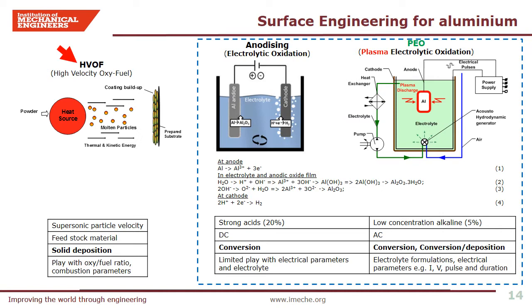Now let's look at the most common electrolytic coating process for aluminum: anodizing. The part — often aluminum — is made an anode, a positive terminal in the electrolytic cell. The part is immersed in an electrolyte consisting of an acid solution with temperature carefully controlled to give the desired properties. For example, in case of hard anodizing, sulfuric acid is maintained between 0 to 5 degrees Celsius, resulting in a hard, dense, dull gray coating. Usually a DC current is applied and the voltage often does not exceed 50 volts. At the anode, aluminum is oxidized to Al³⁺ cations and with the abundance of oxygen ions in the solution, aluminum oxide is formed at the surface, while hydrogen is produced at the cathode surface, typically a stainless steel sheet.